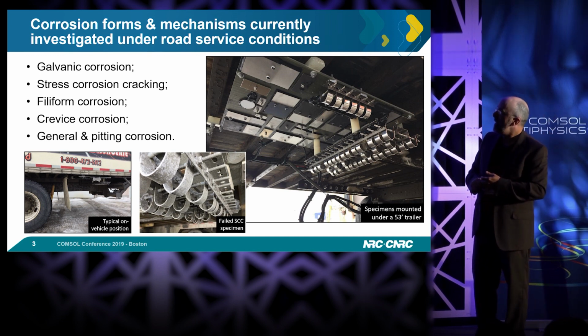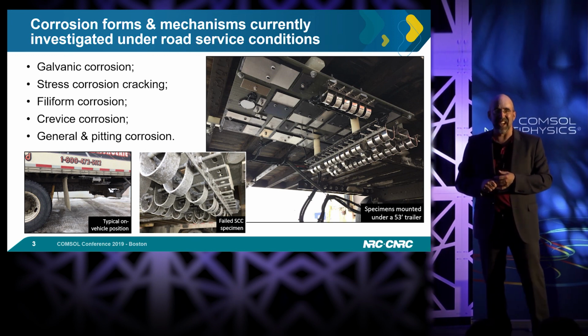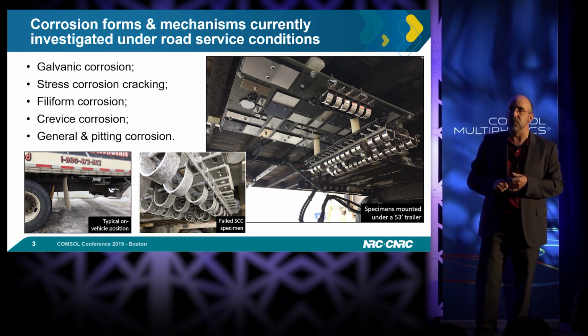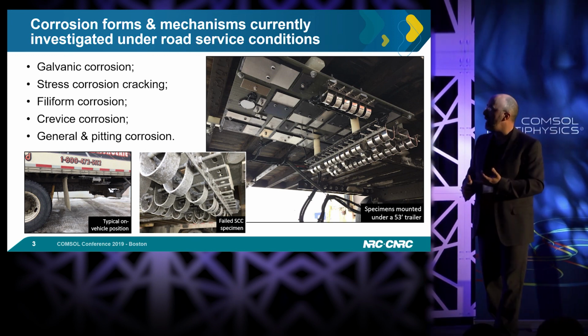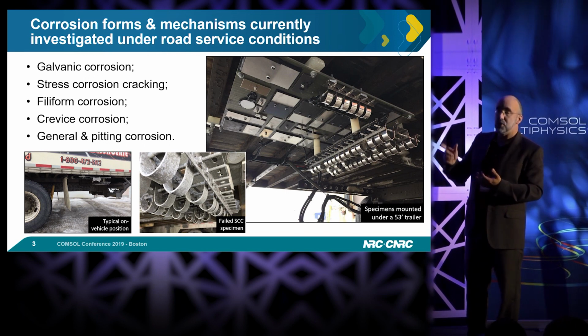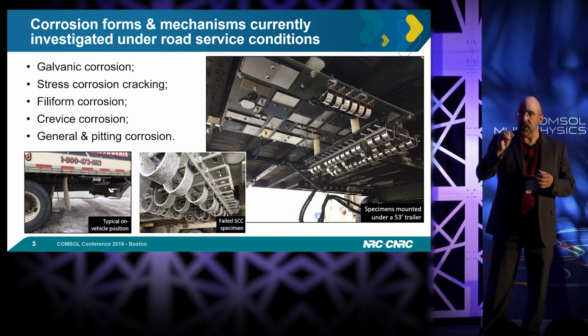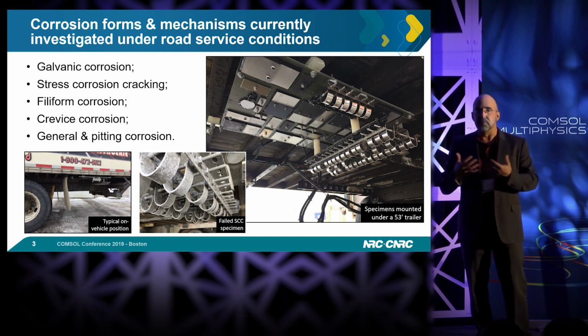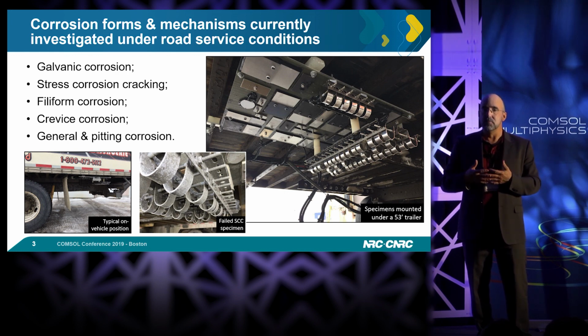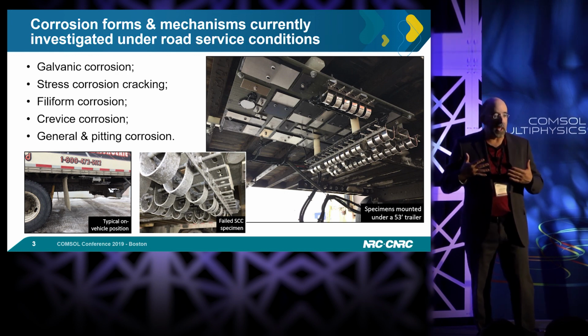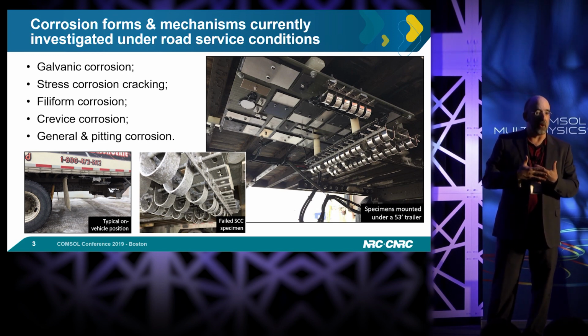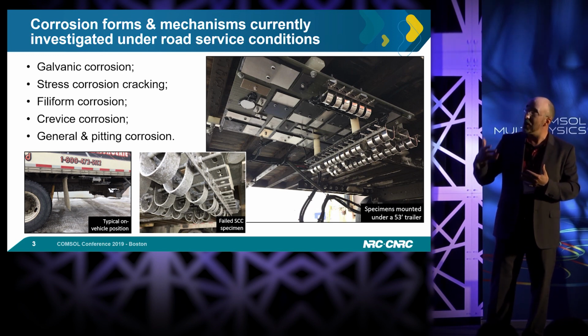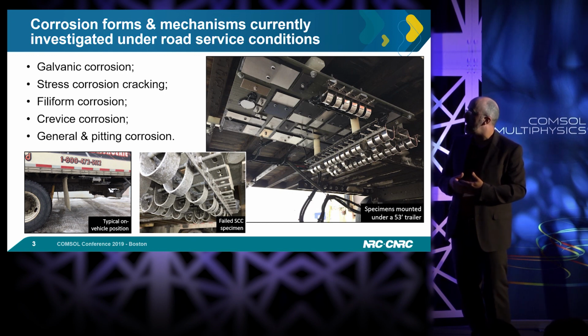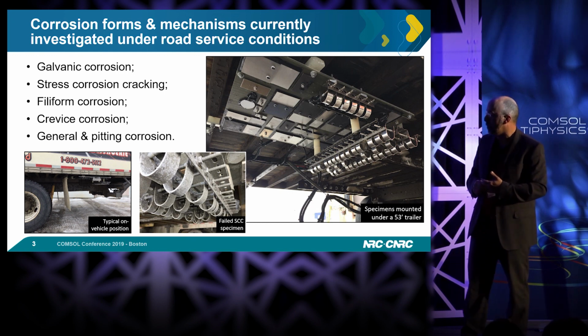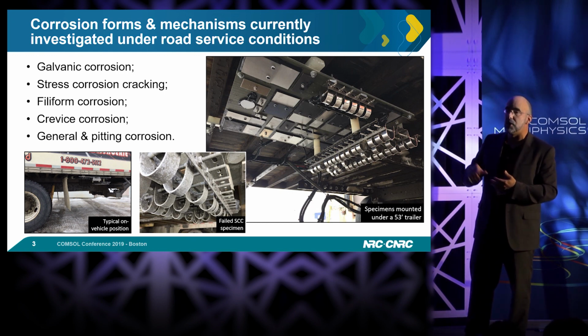So stress corrosion cracking is a real nightmare for people that want to use high-strength aluminum alloys. Filiform corrosion, again, that could be a big issue if you have copper-rich alloys. Crevice corrosion, a crevice is a very tight opening. If you combine different materials, then you may increase the number of joints you will have on your vehicle. Then you increase your chance to have crevice corrosion and general and pitting corrosion for sure.